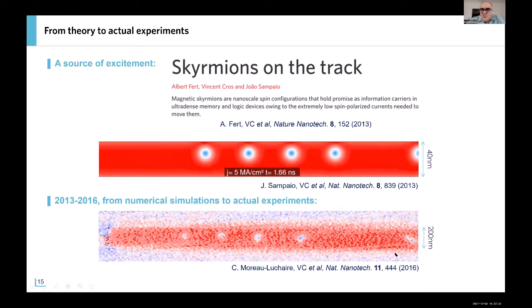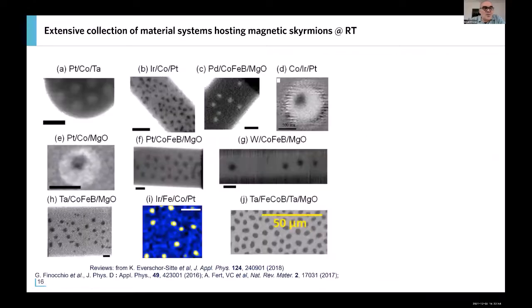And we could observe, about 3 years later, the first room temperature Skyrmions with very small sizes, less than 100 nanometers. This is an image obtained in one of the multilayers I will show later by scanning transmission X-ray microscopy. And you do see here some Skyrmions in the middle of the chart. So I have no time now to make a very detailed state-of-the-art, because it has really been the subject of research of many groups in the world with many different systems.